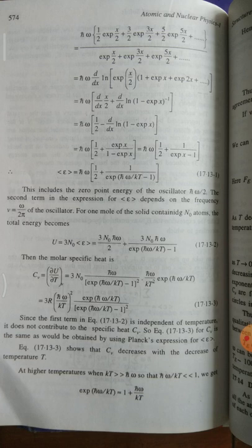The total molar specific heat is Cv equal to dU/dT at constant V, equal to 3N0 into ħω by exp(ħω/kT) minus 1 whole squared, into ħω by kT squared, exp(ħω/kT), which gives 3R (ħω/kT) squared times exp(ħω/kT) by exp(ħω/kT) minus 1 whole squared.